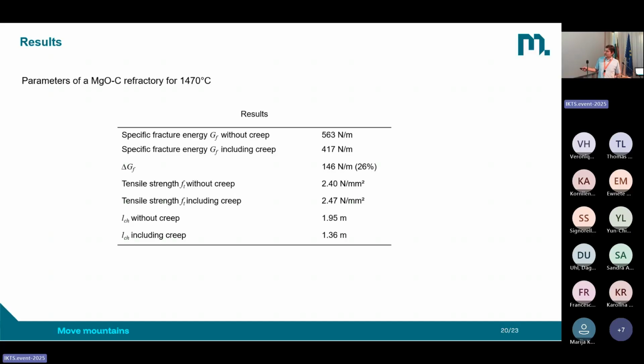For the tensile strength, we see that with including creep, we are getting a higher tensile strength. Why is this the case? Again, because of the contribution of creep, we need more strength to reach the same maximum in the curve. And then we can again calculate the characteristic length for the cases with creep and without creep. And again, we see a significant difference.